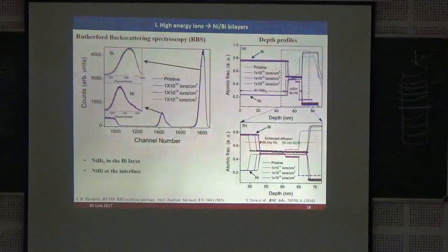So it is mostly aligned from the surface to the interface of nickel and bismuth. You can see this is the bismuth depth profile, and this one is for nickel. From the surface to a depth of almost 50 nanometers it is almost constant, and it must be the NiBi layer. Then it is mostly 50% nickel and 50% bismuth, so it must be NiBi with equal contribution from nickel and bismuth. After that, it is mostly nickel, and a few bismuth atoms are there in the nickel layer.